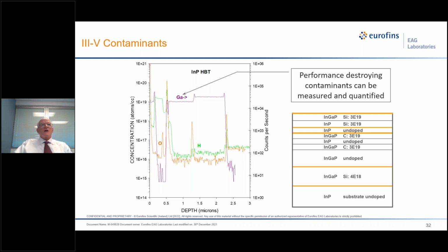We can also follow trace impurities, oxygen and hydrogen. And people are asking a lot about the detection limits of atmospheric contaminants in these layers. They're very important, but they're a problem because these elements are contained in the residual gas in the vacuum system of the SIMS machine, and they're continuously contaminating the surface as you're sputtering it. So the best way of reducing these background levels is to have a very low pressure in the vacuum chamber.